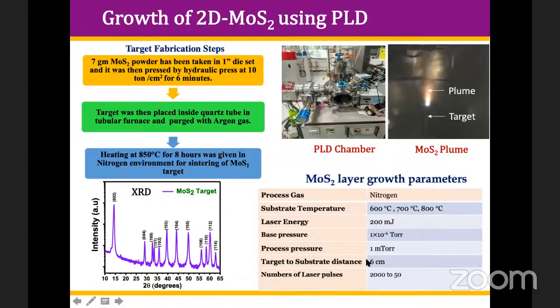Target to substrate distance we can vary, but I have fixed it to 6 centimeter depending upon our experience in the laboratory. And the number of laser pulses we can change from 50 to 2000. 50 is for monolayer and 2000 is for bulk sample.